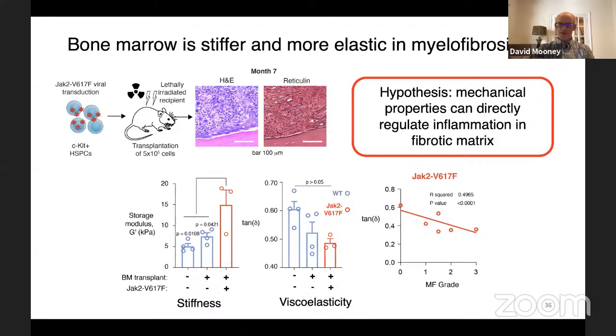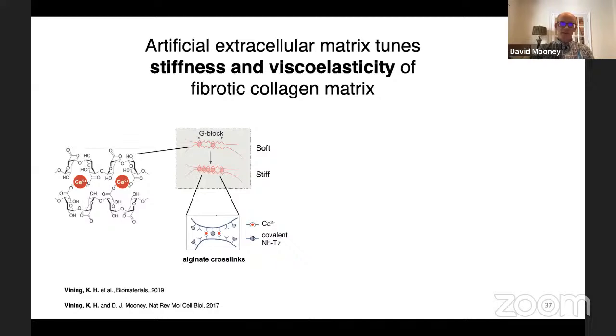So then Kyle addressed the hypothesis that these changes in mechanical properties could directly regulate inflammation in this setting. To do this, he stepped back to an in vitro model, and as collagen is the major extracellular matrix molecule that we know is involved in fibrosis, I won't go into detail because he actually published the system, but he developed an approach to create interpenetrating networks of collagen and alginate.